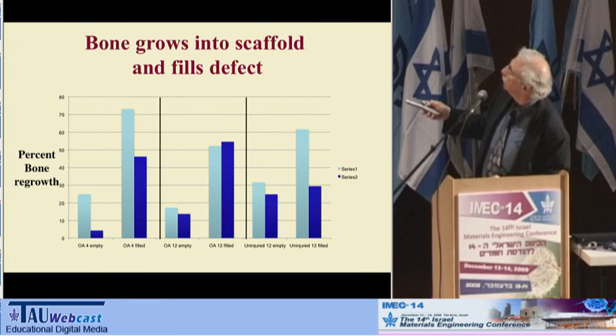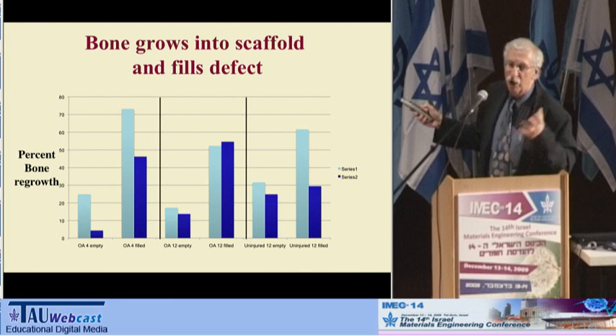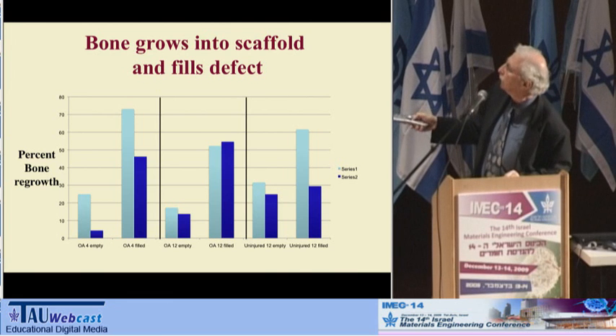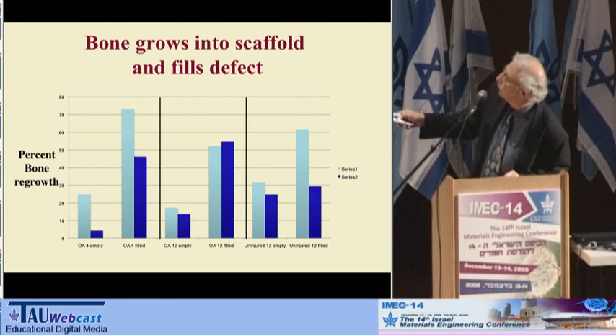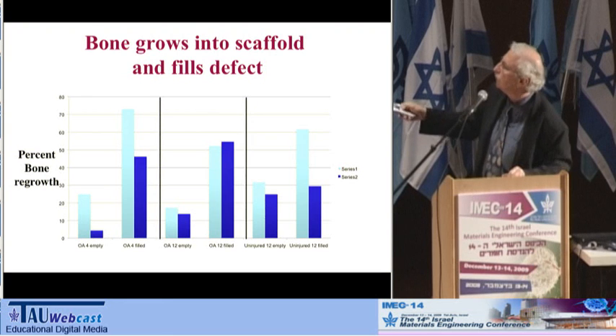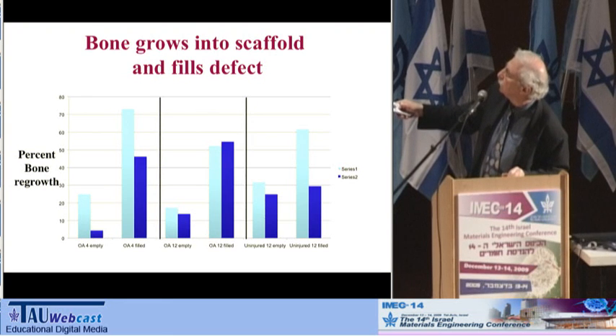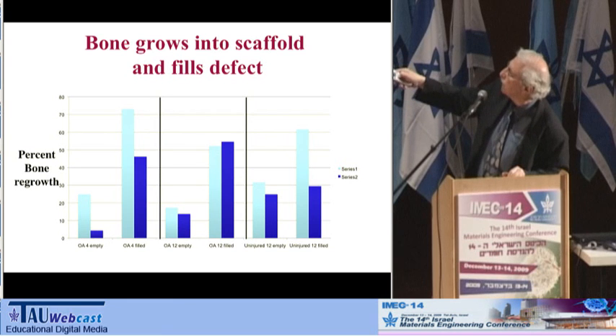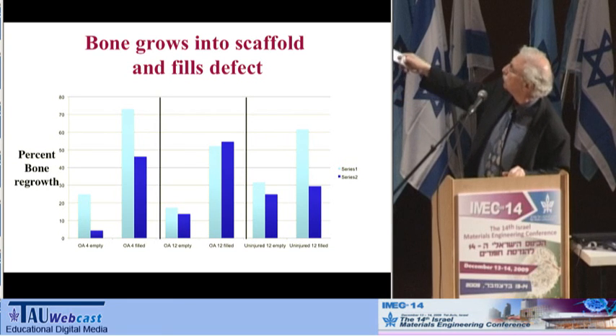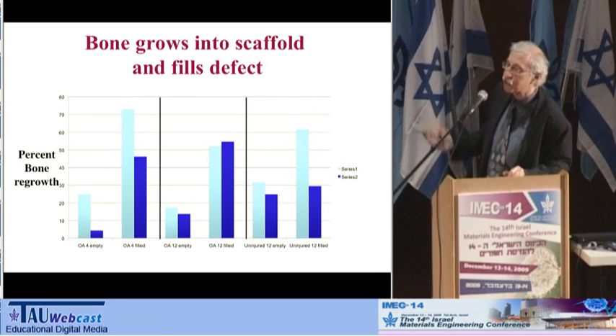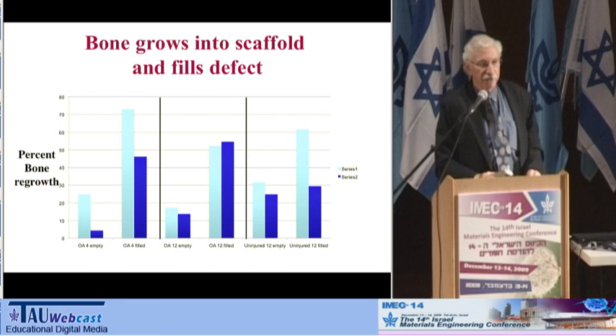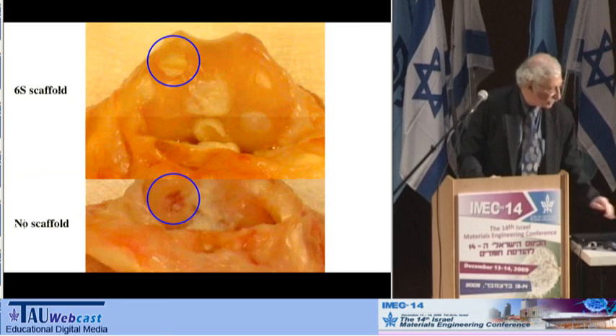And there are two experiments. It's a dark blue bar and a light blue bar. And so here's just the amount of bone regrowth in the empty divot, and then filled with the scaffold. You know, it's got a tremendous amount of bone growth. Empty, filled, tremendous amount. Here's empty, filled. This dark blue one didn't do that well, but clearly most of them regrew the bone very nicely, enthusiastically.